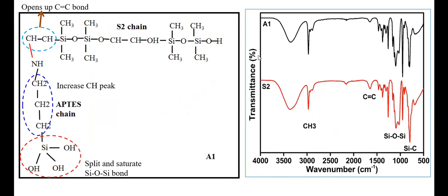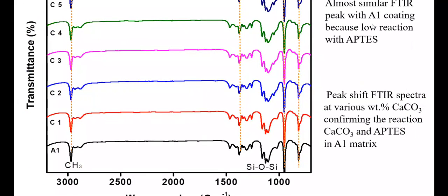Now, when we increase, what will happen here is with the S2 chain, we are using the APTES in order to cross-link the Si-O-Si bond with the binder resin, and this is how the bonding is taking place. Almost similar FTIR peak with A1 coating because of low reaction with APTES, but the peak shift in FTIR spectra with various weight percentage of calcium carbonate confirms the reaction of calcium carbonate and APTES in the A1 matrix.